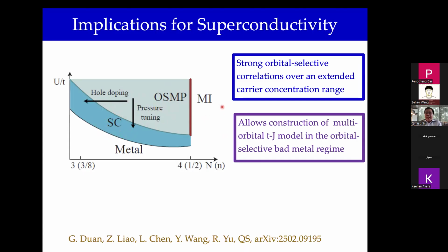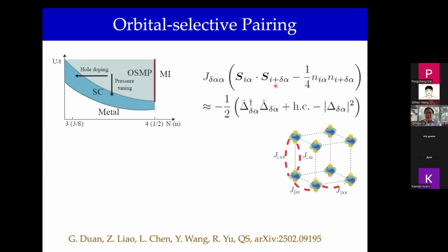So with that in mind, using these as the anchoring point, we can construct the multi-orbital t-J like models and analyze the superconductivity. So this is the exchange interaction. And as I said, the z square orbital is expected to have very large kinetic coupling out of the plane. And so that should lead to substantial J interaction. The x square minus y square orbitals would also have this interlayer exchange interaction, but presumably weaker. And there are other channels of interactions in the plane.